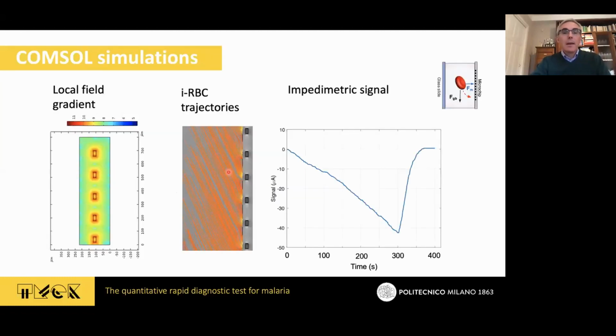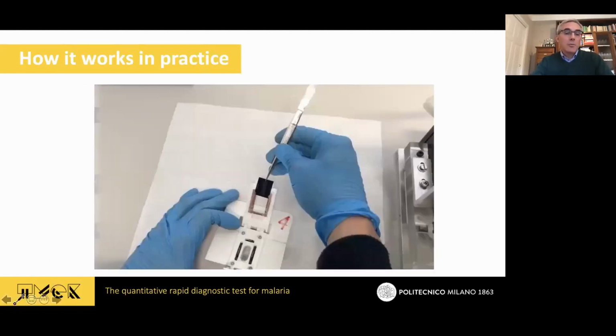that you are targeting. And this is a simulation made by computer that shows the trajectory. You see that initially they follow this oblique trajectory. They are attracted by the external gradient till they reach more or less the surface of the chip. They feel now the local gradient. They are attracted towards the electrode. And in this way, we are able also to simulate the change of the impedance, which is due to the capture by the electrodes, and finally produces the change in the resistance which is seen by the electronics. And this is how it works in practice.